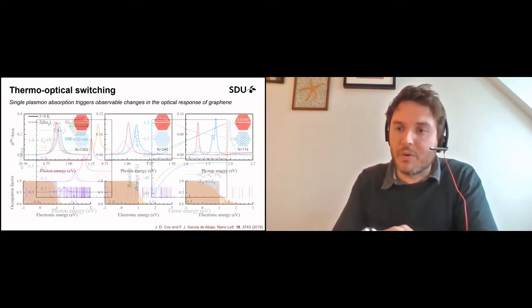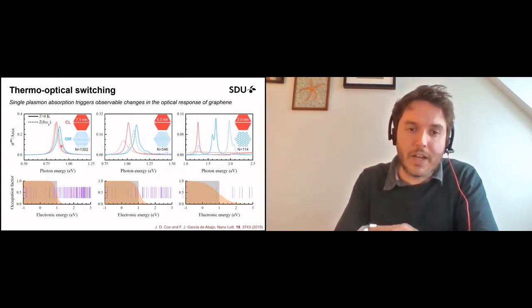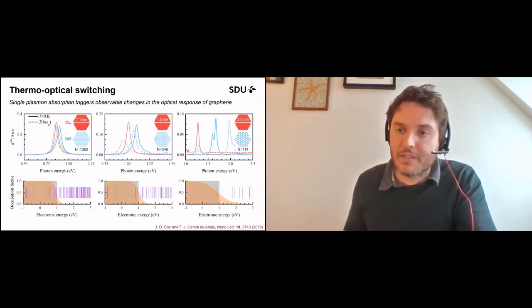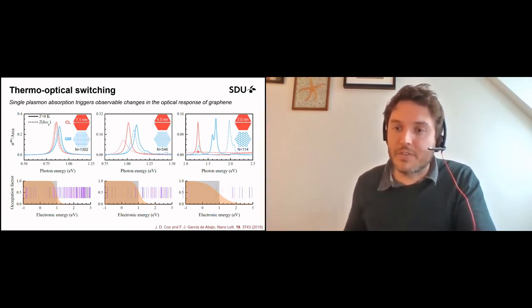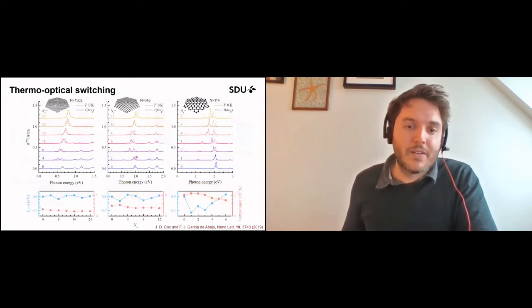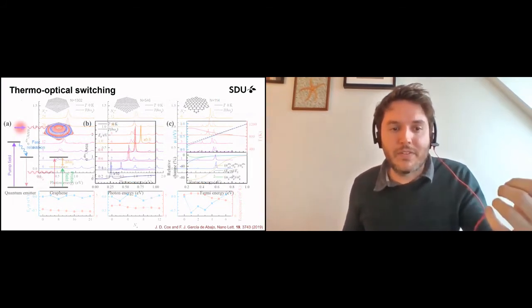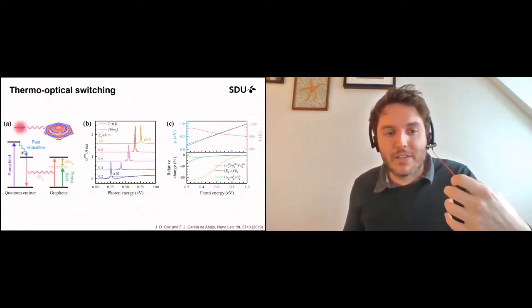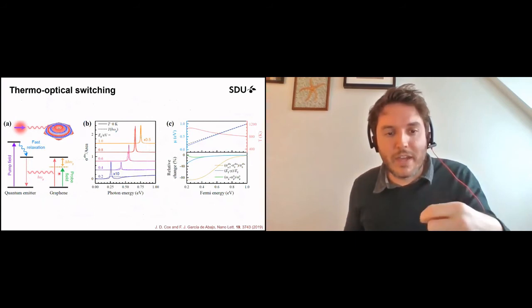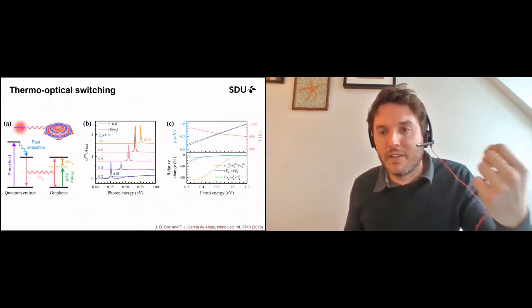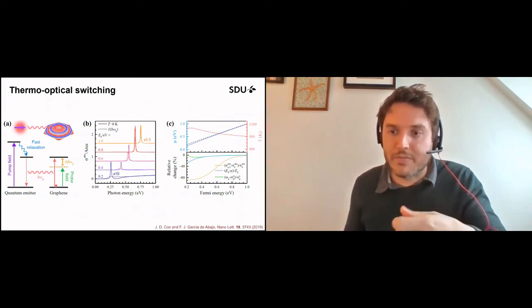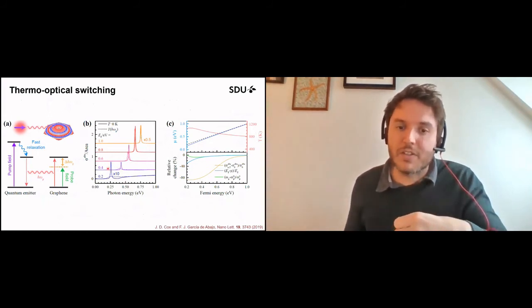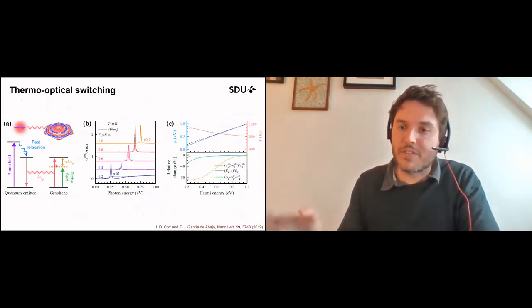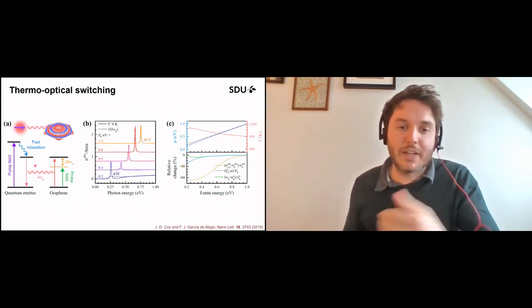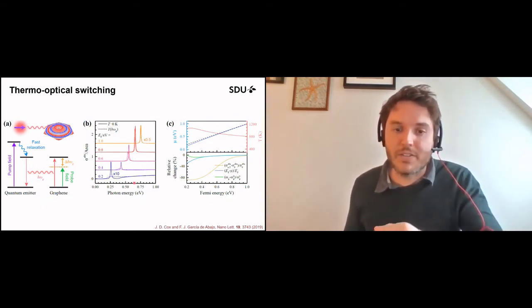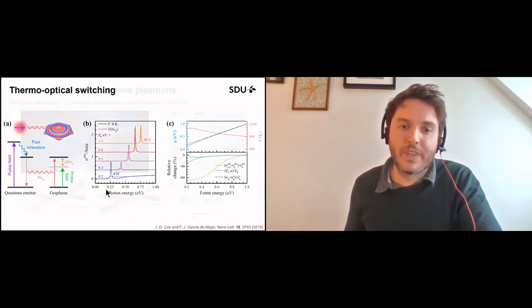I should also mention that this was studied both using classical models and also atomistic descriptions for very small islands, but qualitatively the physics is the same. Actually, for smaller islands, you're more sensitive to quantum finite size effects. But the story is, at the end of the day, if you can couple this quantum emitter to a graphene island, and it is excited by an optical field and decays, spontaneously emits light, exciting a plasmon, that plasmon will then be absorbed by the graphene in the order of tens of femtoseconds, and it will trigger a dramatic change in the optical response. So already you have effectively a single photon blockade, because the next absorption event won't occur in the same way since you've moved the optical resonance.